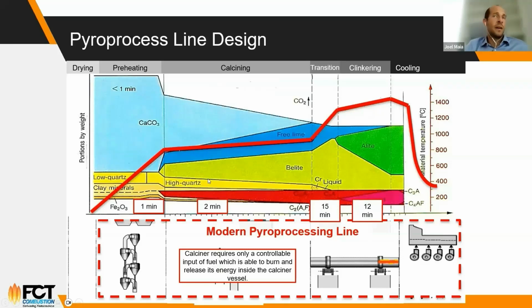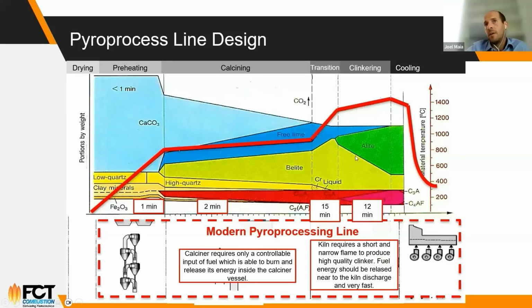And what is important to say, as I told before, is that we have to differentiate between the preparation phase and the clinkerization. In the preparation phase, what is important is just a controllable input of alternative fuel, and that the calciner itself and the injection points and so on allow the release of energy inside the calciner itself. We don't want fuel going out of the calciner, burning in the preheater tower, or coming inside the kiln inlet, and so on. And then at the kiln, as I said, this part of the chart has a very strong influence on the quality of the product.